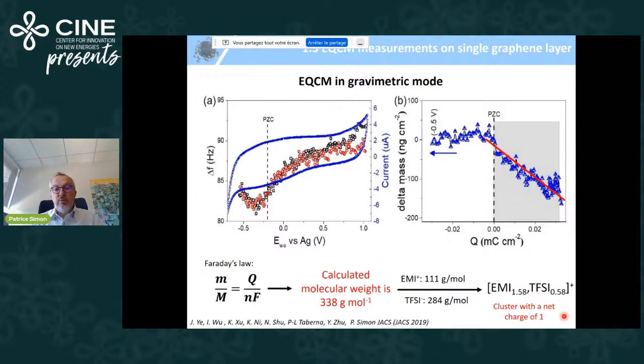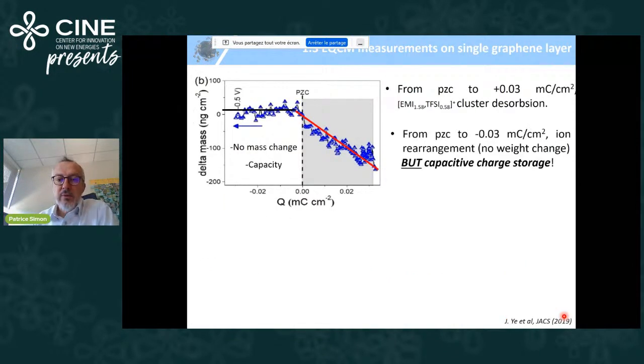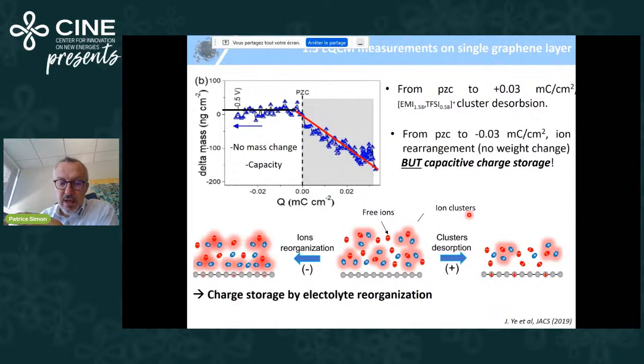So this could be the case because in neat EMI TFSI, there is no solvent to screen the interactions between the ions. And what is also very interesting is that for negative polarization, there is no weight change. There is no net ion flux in or out of the single layer graphene. However, if you remember the cyclic voltammetry, there is still a capacitive charge storage mechanism. So this shows that you have a storage mechanism, but no net ion flux.